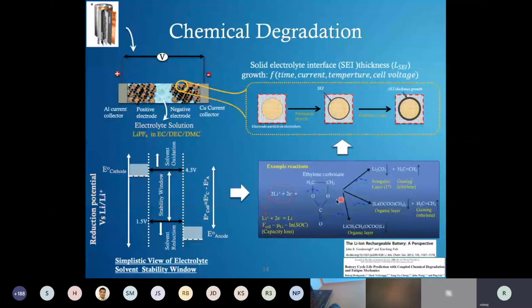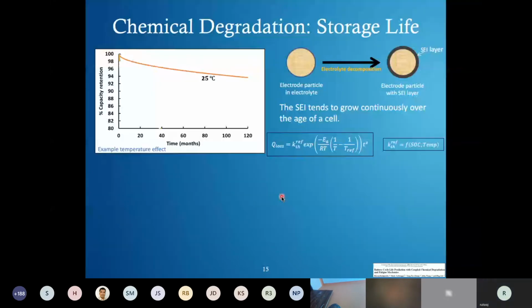These reactions continue over the life of the cell, and the thickness of this layer gradually increases over time. As these reactions are happening, more and more lithium is being consumed. So this is the leak that we were talking about in the previous example. These reactions act like a leak, and they are eating away all the lithium from your system. The SEI layer tends to grow over the age of the cell continuously, whether you're storing or using the cell. So there is degradation over time.